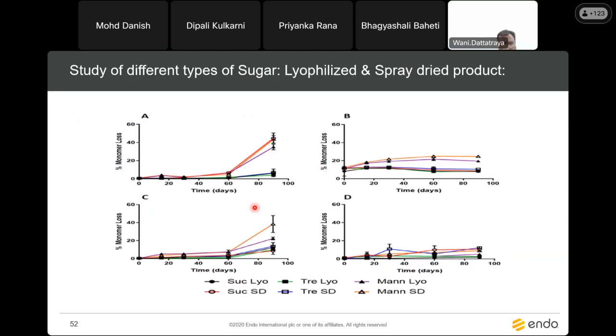So this is one application. Here what we have done, we have 4 formulations with different sugar moieties. These are sucrose, trehalose, and mannitol, and different processes. One is lyophilized, one is spray dried. So we have drawn this data, and here we can get what percentage of the monomer is forming. Based on this, we can conclude which polymer, which technique, and which sugar moiety we have to use to optimize the formulation, and whether we have to go with the lyophilization or spray drying technique.